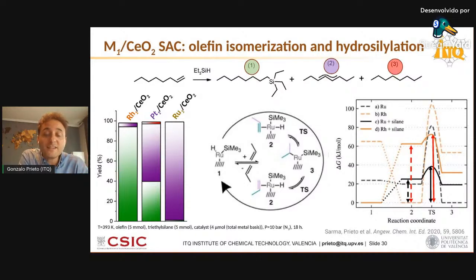On the platinum catalyst, these two reactions compete on the same active center. On the rhodium and ruthenium catalyst, these two reactions are decoupled on two different catalysts. It's a perfect situation for a tandem integration of the two. We could actually track back the reasons for this specific difference in the behavior of rhodium and ruthenium using in situ spectroscopy and, again, DFT modeling.